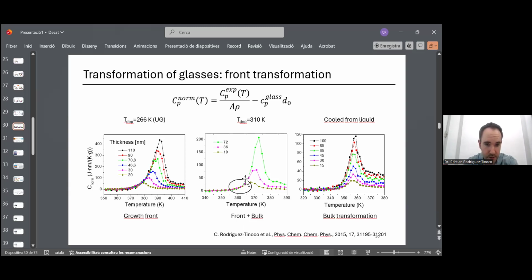Okay, in the ultrastable glass, this was happening up to a larger temperature. Here, only in this region, in the fast cool glass. So it means that here we still have some degree of transformation that takes place via front propagation. And what about the velocity of propagation in this case?